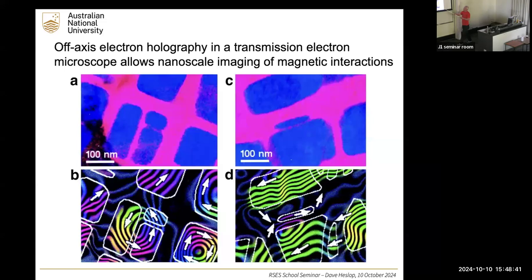So we've got again the magnetite and the non-magnetic matrix here. The outlines of the particles are the same down here. So this magnetite particle here, you can see its field is forming a vortex, just like we saw earlier. But when you get particles close to each other, the energy minimization starts working cooperatively. So we've got three particles here that probably individually would not form a vortex, but in cooperation, they lower their energy by acting together and forming a vortex.